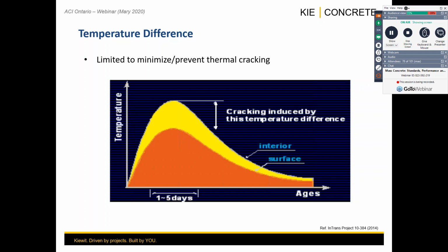You don't want to be trapped by heat of hydration, leaving it inside of that insulation and trapping it, because eventually that's going to cause a longer time for you to manage those temperatures as they're released and normalize with the environment, and you pretty much are not going to be able to build a lot of work. So you need to make sure that you establish a gradual heat loss from the surfaces. That's a key element. You want to allow temperature difference to occur, but you need to create a gradual heat loss, and that gradual heat loss needs to obviously take that into consideration. So that's important to understand.